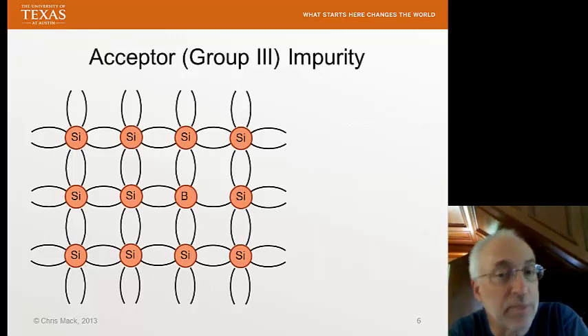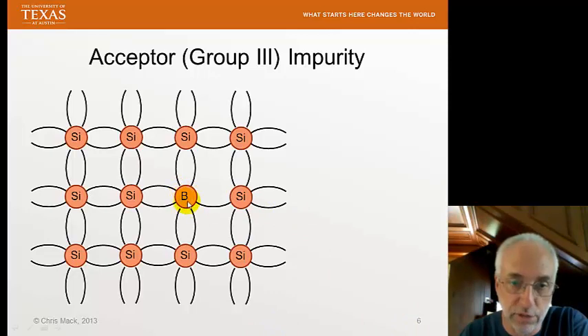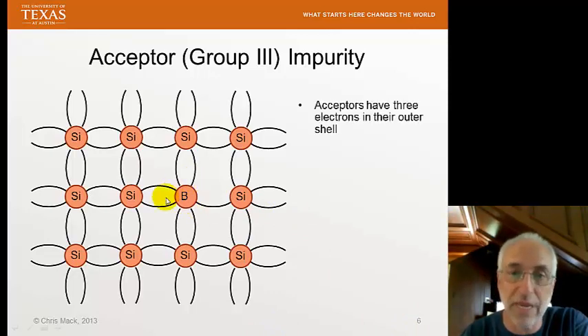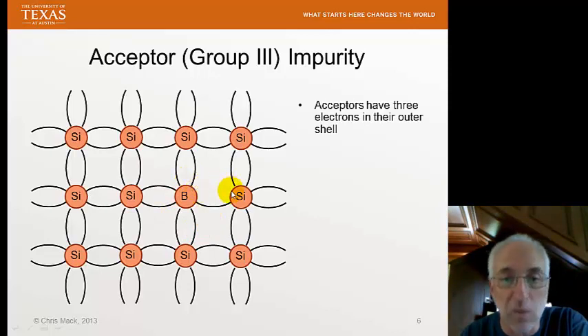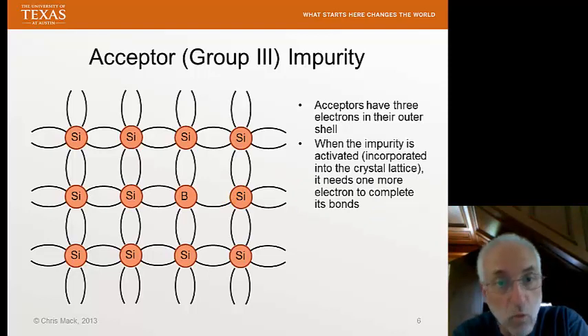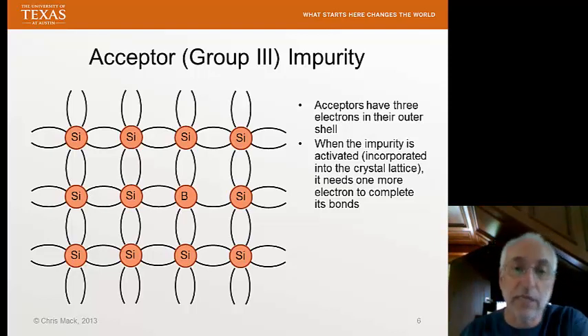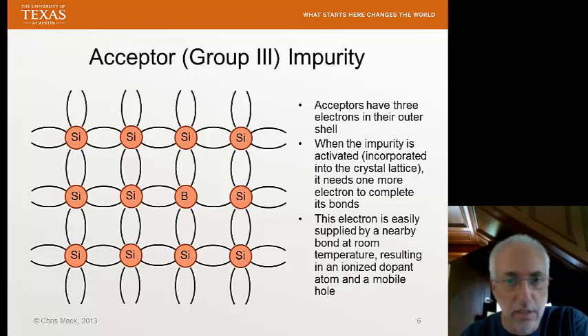So it changes the concentration of the mobile electrons in the semiconductor. And that's what we're doing. We're adding dopants to increase, in this case, increase N, the concentration of the mobile charge carriers. We call these kinds of group 5 dopants or impurities donors because they donate an electron. Acceptors, on the other hand, accept electrons. Here we show boron. It's incorporated into the crystal structure here. And because it only has three outer shell electrons, it's missing one. So it doesn't have a complete bond here, shown next to its silicon. It's missing an electron. It wants an electron there so that it can complete its shell.